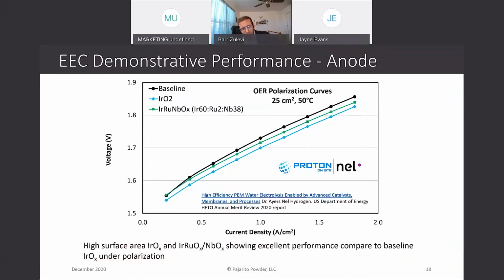Here are a couple of cases of demonstrations that we've had where we have an iridium niobium oxide material in the green line here that's being compared to the baseline oxide. This test was conducted by Proton OnSite, NEL, who's the world's leader in electrolyzers. And what we see here is that an iridium oxide supported on niobium is able to achieve a better performance than a baseline iridium at a 40% reduction in iridium, which is a huge improvement.